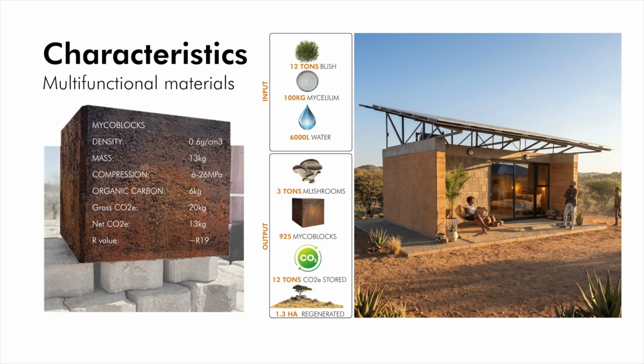But actually, every block that we made stored about 1.5 times its own weight in CO2. And that sounds nearly impossible. How could you get more air into that than it actually weighs? It's because the CO2 molecule, as it's in the air, is much heavier than the organic carbon that the plant draws down during its life cycle and stores into the plant material that then goes on to be stored in here. So if you look at CO2 over C, it's about 3.5 times the weight of that material. And then when you multiply that out with 40% of the biomass of the block being organic carbon, you get about 1.5 times its own weight in CO2.